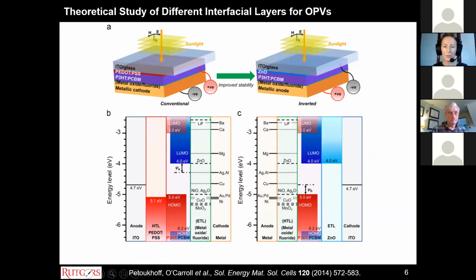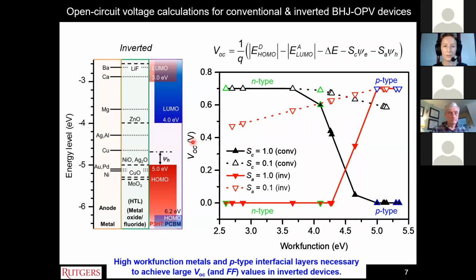So this was early work by one of my graduate students, Chris Petoukhoff, that we published back in 2014, but I'm using it as a motivation for why we're studying certain oxides. And what you can see here is in the inverted devices, if you look, for example, at silver oxide, Ag2O, it matches very well with the HOMO level of P3HT. So it's potentially very good for charge collection, and will reduce any barriers to charge collection, hole collection in particular.